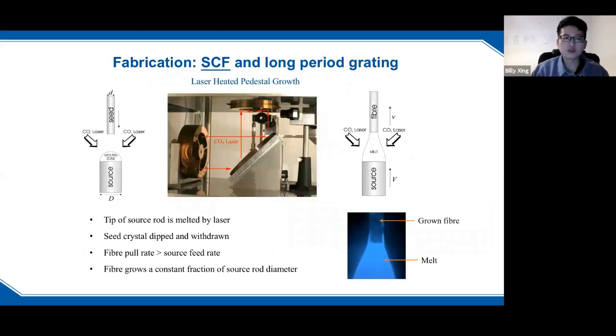Let me introduce the fabrication process of single crystal fiber and the long period grating. First, how do we fabricate single crystal fiber? The technique we use is laser-heated pedestal growth. As you can see in the picture, we have a source rod, and we use a high-power CO2 laser to melt the tip of the source rod to create a melting zone, dip the fiber seed inside this melting zone, and draw the fiber. The fiber pull rate is larger than the source feed rate, so the fiber grows as a constant fraction of the source rod diameter. In this picture, you can see the melt, a picture from the camera we took in the lab, and this is our fiber, and this is our setup. This is the basic fabrication method we use.